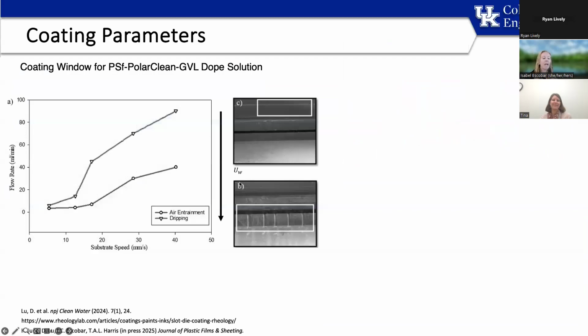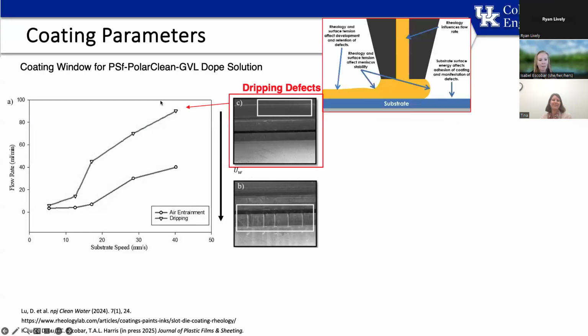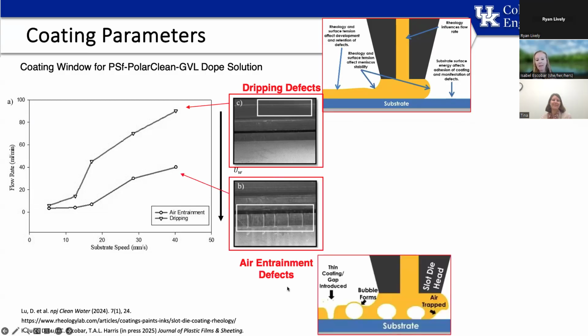And after making many of these, we can do these by hand, and this part of our casting window was developed by hand here, and you can see we have a few data points. We have 8 data points. The top are the dripping effects. Again, the flow rate is too high, and we start to get unevenness at the edges of the membrane. The bottom is air entrapment. We start to have bubbles exploding within the membrane.